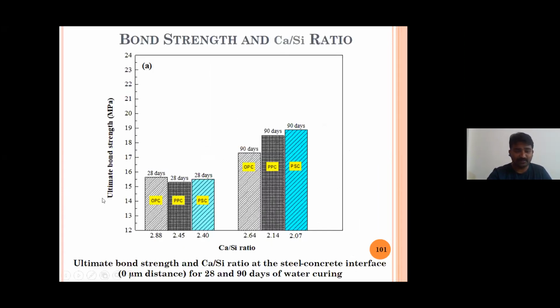So we have studied that also, the ultimate bond strength. This is for OPC, PPC and PSC. The ultimate bond strength and Ca by Si ratio of steel concrete interface at 28 and 90 days of curing. These are 28 days, OPC, PPC, PSC, ultimate bond strengths. PSC and OPC are almost closer. PPC is a little lesser. And these are the Ca by Si ratios, 2.88, 2.45 and 2.40.